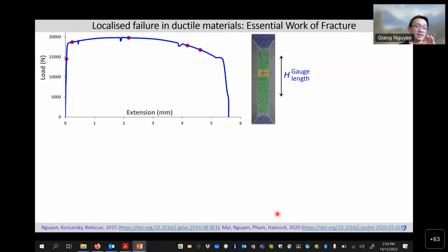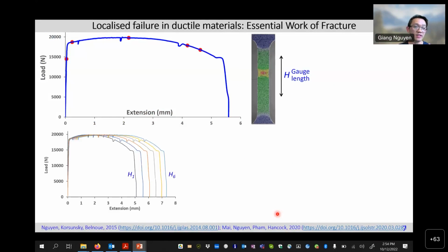The energy in this case is the essential work of fracture for metal. Okay, so say I have the gauge length here. I change the gauge length from H1 to H6 here. I get different curves, because in this case our curves depend on the gauge length extension here.